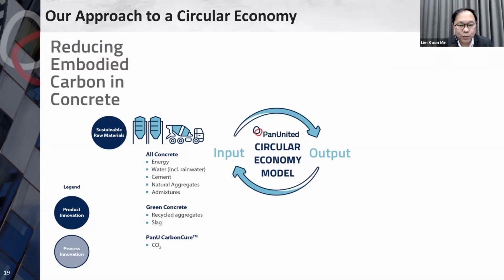So by zooming in on cement, we start to ask ourselves, how can we replace this with other alternatives, for example GGBFS, which typically has lower than 10% of the carbon footprint of ordinary Portland cement. And next, we also ask ourselves, can we further reduce this cement? In Pan United CarbonCure concrete, by injecting CO2 in the concrete, we are able to reduce the cement. Thus, we are able to further reduce the upfront carbon footprint in these concrete products.